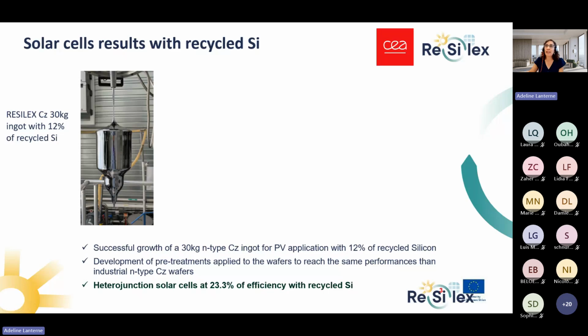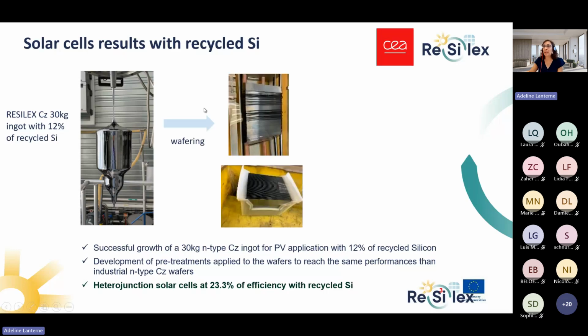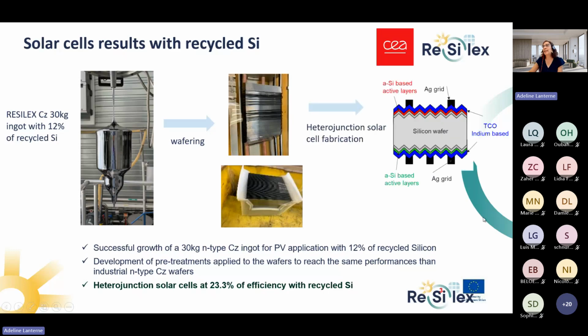And for this recycled silicon, they managed to reach a purity of 5N in the project, and so we could use it to grow this ingot with properties suitable for solar cell application. And so that was our first success. And then we sliced the whole ingot into wafers. And in the end, we processed heterojunction solar cells on these wafers.